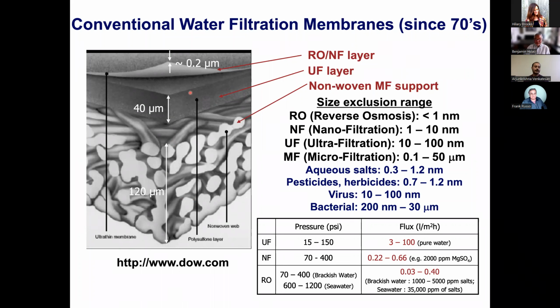But this is only for ultrafiltration, and to make it into nanofiltration or reverse osmosis, you coat a very, very thin layer of cross-linked polyamide film on top of it. And pore size can be less than 1 nanometer, so you can remove salt ions. Then all of a sudden, there's a very thin coating, and it will increase your price point by almost 2 orders of magnitude. So immediately I realized that there's something about nanofibers, because if you add something at nanoscale on the surface, a very small amount, you increase the value of these membranes by almost orders of magnitude.